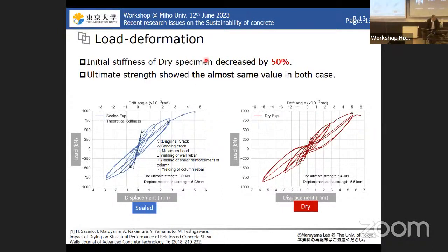Actually, the initial stiffness, so you can see that's the stiffness here, this stiffness is decreased by 50%. So it is quite large. And ultimate strength is almost comparable here, but the deformation at the ultimate loading capacity is a little bit increased. So from a structural performance point of view, these two characteristics are very, very important.